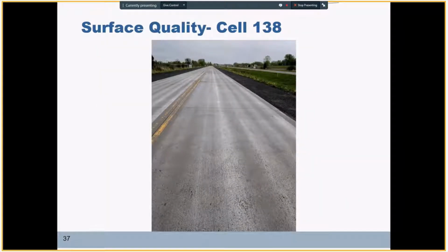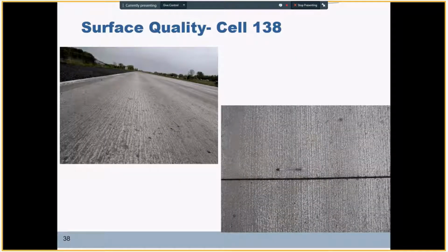Here I have some pictures from the surface of the pavements to refresh our minds on the pavement texture characteristics. These pictures were taken in May 2019, so the most updated pictures that I have. Here we have cell 138, acceptable surface quality, no change in quality of the surface after 2 years of exposure to environmental conditions in Minnesota. Here's a close-up view of the transverse joint - very good joint quality, very good surface quality, and another view of the surface texture for cell 138 with low cementitious content.